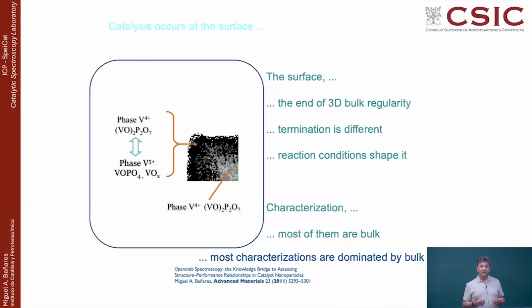The classical case was the VPO catalyst, which is vanadyl pyrophosphate. Vanadyl pyrophosphate catalyst is vanadium 4+. But you characterize it and you always see vanadium 5+. That cannot be, it must be wrong, forget it. No, but you have vanadium 5+, no way. Yes, you do. Why? Because the surface of the vanadyl pyrophosphate is no vanadyl pyrophosphate. You get dispersed vanadium oxides. We saw it with iron molybdate, we see it with vanadyl pyrophosphate.